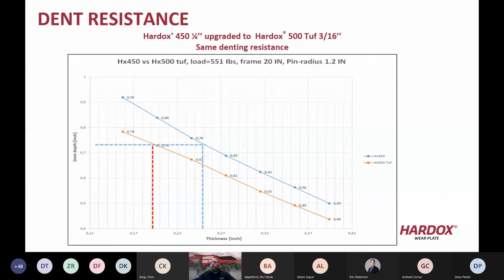And then if you look at dent resistance, if you have a container or dump body or something that's taking a lot of impact and abuse, we've seen where 1/4 inch Hardox 450 going to Hardox 500 Tough 3/16 of an inch thick, it's taking the same dent resistance as the 1/4 inch Hardox 450. So the 1/4 inch Hardox 450 and the 3/16 500 Tough would have about the same wear life and also